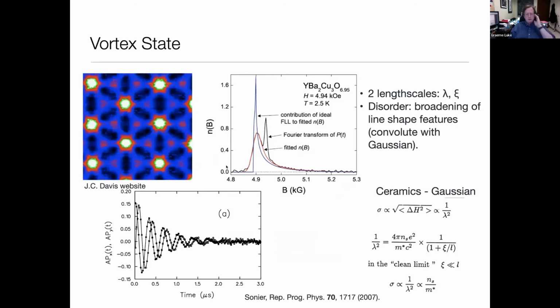Okay. So once we have a type 2 superconductor, which most interesting materials are, one of the things we can look at is the so-called vortex state. If we apply a magnetic field, the field penetrates the superconductor in the form of vortices, which repel each other, and so they form a lattice. Now the lattice constant is given by the strength of the magnetic field, because each vortex carries 1 quantum of magnetic flux, and so you can calculate the density of vortices by just knowing the applied field. So here's an STM picture showing you the density of states as you tunnel into different directions. However, around each vortex, which is essentially a normal tube, you have a supercurrent flowing around that, which then screens the magnetic fields out of the bulk.